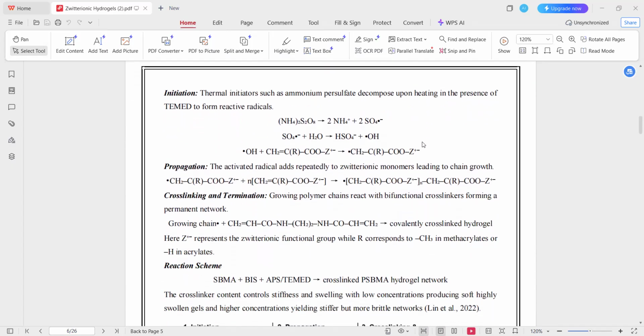The process begins with initiation, where a thermal initiator such as ammonium persulfate decomposes upon heating. This decomposition generates sulfate radical species, which are highly reactive. These sulfate radicals react with water to form hydroxyl radicals, and these hydroxyl radicals then attack the vinyl double bond present in the zwitterionic monomers, such as sulfobetaine methacrylate. As soon as the radical adds to the monomer, a new reactive radical center is created on the polymer chain.